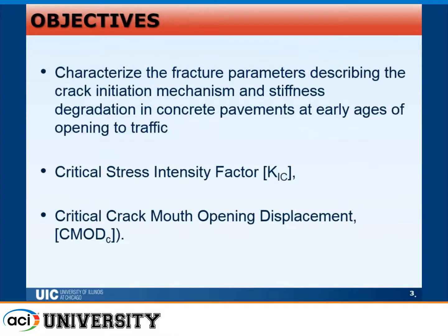concrete pavement. The objective of this study is to characterize the fracture parameters describing the crack initiation mechanism and the stiffness degradation in concrete pavements at early age: the critical stress intensity factor and the critical crack mouth opening displacement. Obviously those two are the main fracture mechanics parameters, and they are used to identify the crack initiation and the stiffness degradation, especially the compliance factor that is associated with the loading and the crack propagation at the vicinity of a crack tip in the concrete pavement.